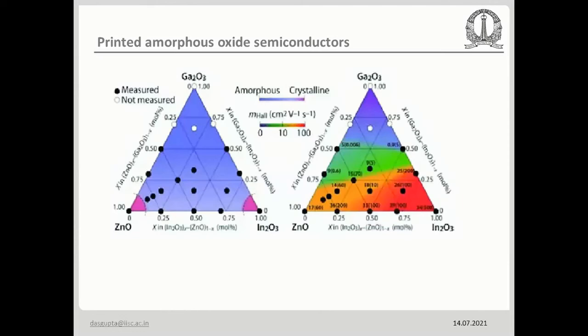Here I give you another view graph just to promote this idea of amorphous oxide semiconductor a bit further. This is between indium oxide, zinc oxide, and gallium oxide. We can see that only pure indium oxide and zinc oxide are crystalline, but everywhere else these are amorphous, and this is a mobility contour.